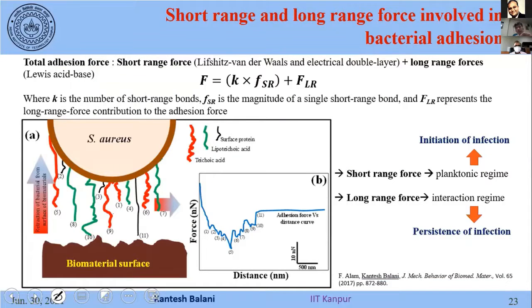But once we have the forces, we can delineate them into short range force and long range force. So the short range force basically conveys how much infection I can get, the initiation of infection, and the long range force will convey how strong is that bond. So it's more like a chain. How strong that chain is will be given by this FLR and the number.